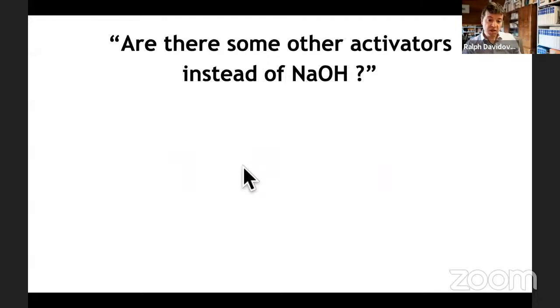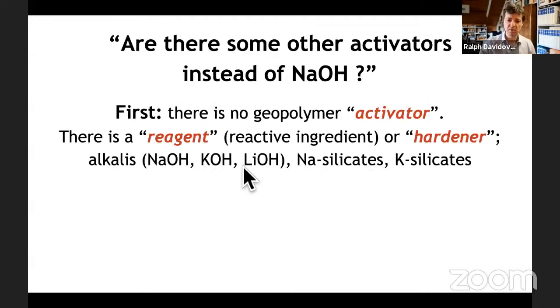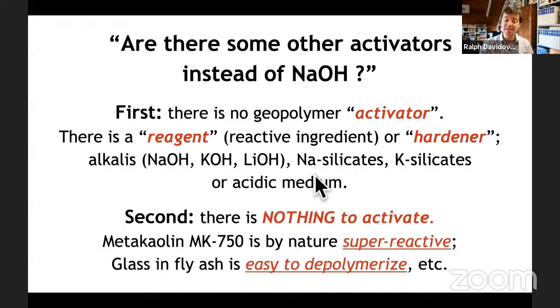I receive some messages. For example, are there some other activators instead of NaOH? First, there is no geopolymer activator. There is a reagent, a reactive ingredient or hardener. We are using alkalis, of course, NaOH, KOH, LiOH, sodium silicate, potassium silicates, or acidic medium. We use also acidic. Second, there is nothing to activate because metakaolin is by nature super reactive. So you don't have to activate, it is a reactive material.